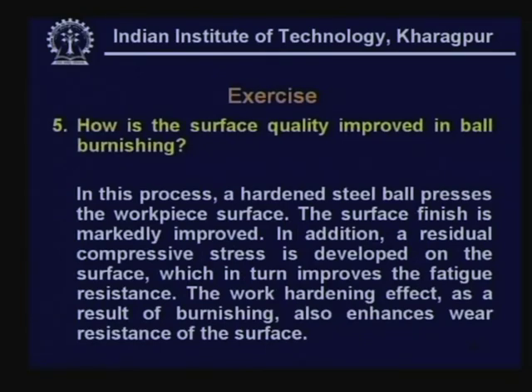How is the surface quality improved in ball burnishing? Actually in this case a hardened steel ball is used for improving the surface integrity of the workpiece. By this rolling action material is not removed, but there is a smearing action. By this smearing action surface finish is sizably improved, but what is more, we can induce compressive stress on the surface, which immediately translates into enhancement of the resistance to fatigue during alternating stress.